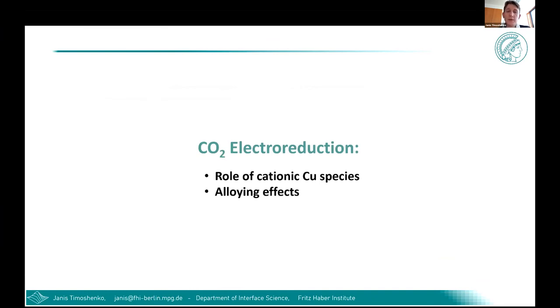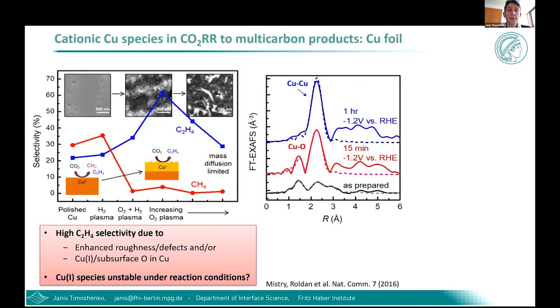So in the remaining part of the talk, I will illustrate the power of X-ray absorption on a few selected case studies, mostly in the context of CO2 electroreduction, but similarly it can be used to study many other electrochemical processes. But in the context of CO2 electroreduction, one particularly controversial topic is the role of oxidized copper species for a conversion of CO2 into multi-carbon products such as ethylene or ethanol. So in general, CO2 electroreduction occurs under quite negative applied potentials, which means that we expect our catalyst to be mostly reduced, mostly metallic under reaction conditions. At the same time, in literature, there is increasing amount of evidence that oxidized copper species can be actually beneficial for CO2 conversion into products like ethylene or ethanol.